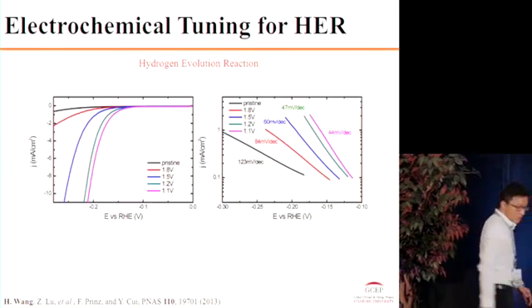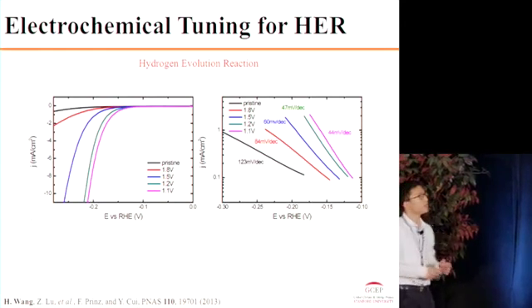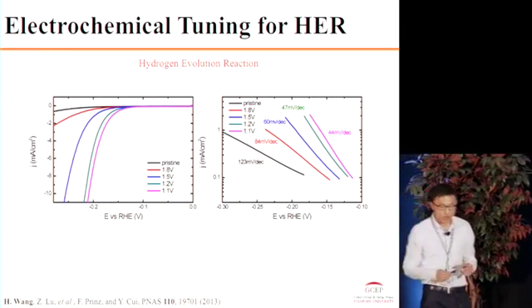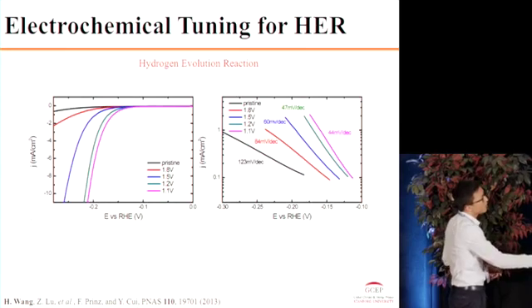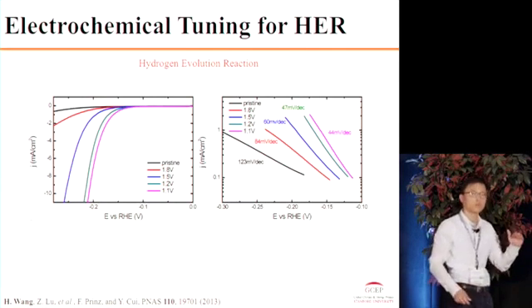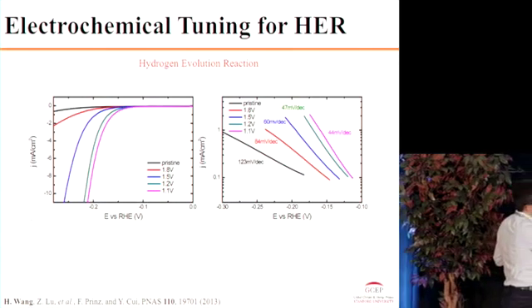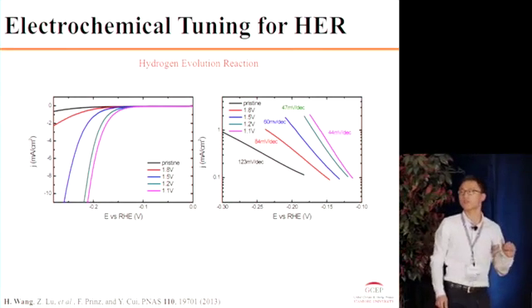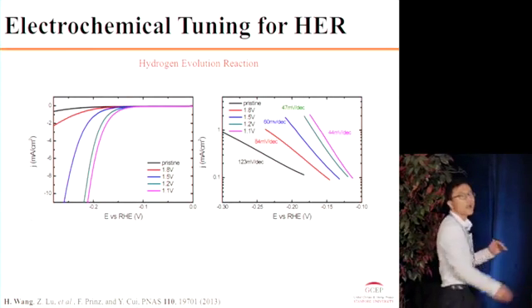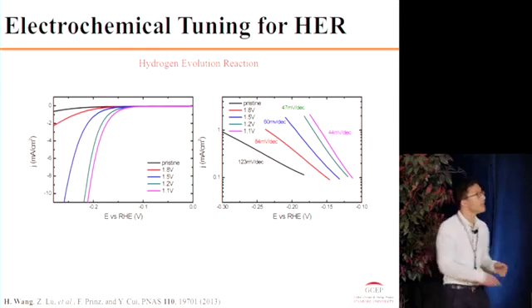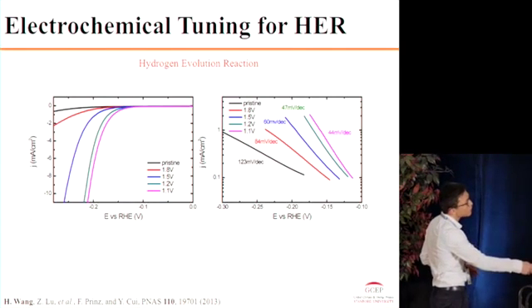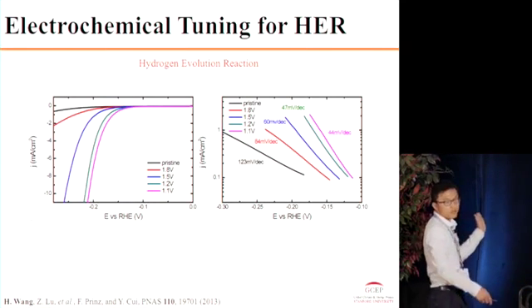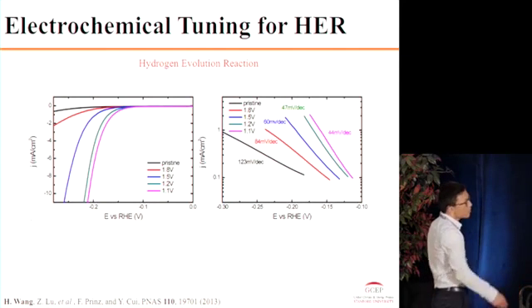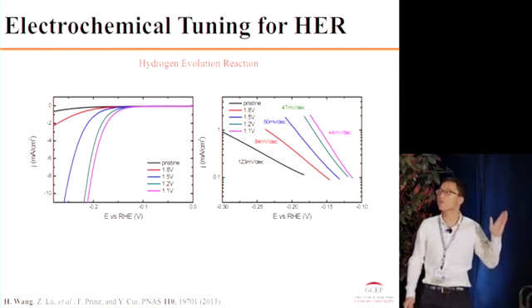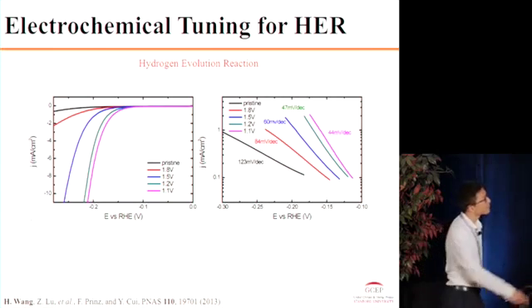And we finally end up testing the hydrogen evolution catalytic activity of this electrochemically tuned molybdenum sulfide thin film. As we can see, with a lower and lower lithiation voltage, we can get higher and higher HER activity. And we can also see that the Tafel slope is reduced from 120 all the way to 40, which is a very low Tafel slope.